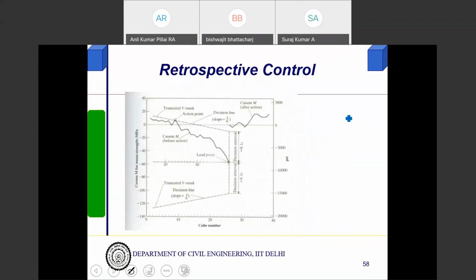So this CUSUM technique can be used to actually identify whether things are going bad or you are designing. And once you have found that it's gone out of the mask, you redesign them, you change the mix proportion. So you see, this is to be done at the site. It cannot be done at the IIT laboratory, which is normally done by most of the contractors.